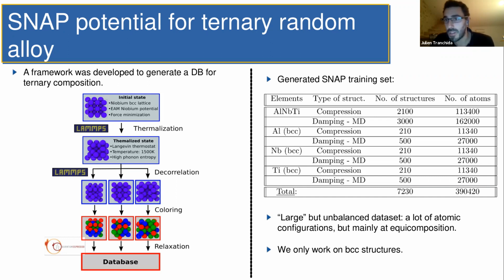Aluminum, niobium, titanium, sorry, I didn't say that, is supposed to be BCC. In practice, when we ran all the calculations, we discovered that it's not really, as the experimentalists at Sandia were believing, that BCC. It's kind of like an amorphous phase in a lot of configurations. But anyway, we tried to focus on BCC structures. And so as you can see, aluminum and titanium here are in BCC phases, which is not, of course, the actual phases. They're supposed to be FCC and HCP. But again, it's an approximation.